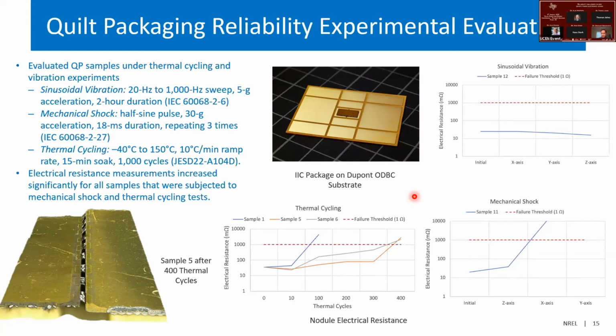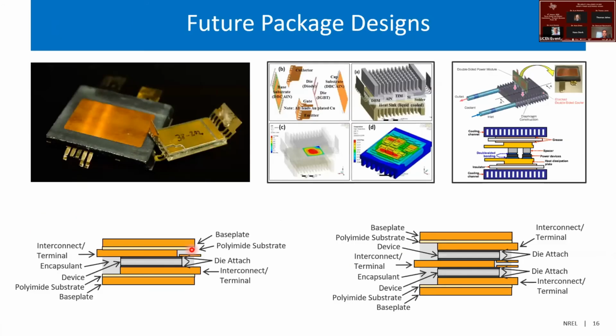Certainly the reliability could be improved. This shows the quilt interconnects, but also the attachment of the devices themselves, the solder or the bonded interface attached. That also, I think, is delaminating. There's a little bit of a confounding effect as can often happen, and that's where some kind of a torsion effect going on here. But overall, working with collaborators on trying to improve these packaging configurations.